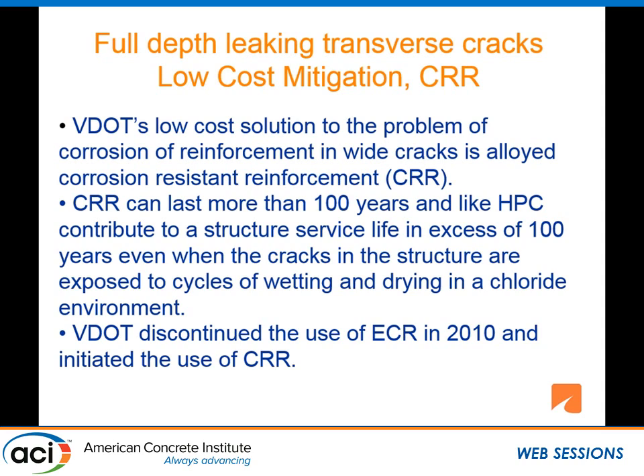VDOT discontinued the use of epoxy-coated rebar in 2010 after this problem with the bridge deck on I-81. We had recommended to the bridge engineer changing to stainless or other corrosion-resistant reinforcement. Richard had recommended that for years, and we finally decided we were going to quit making this recommendation. Then after the bridge engineer in Virginia drove down and saw this hole in this bridge on I-81, he immediately went back to the office and wrote the memorandum indicating we're going to corrosion-resistant reinforcement. It took a failure to get VDOT to make this change. It's amazing in our life that we don't change anything until we have a failure. Fortunately, this time there was no accident or injury.